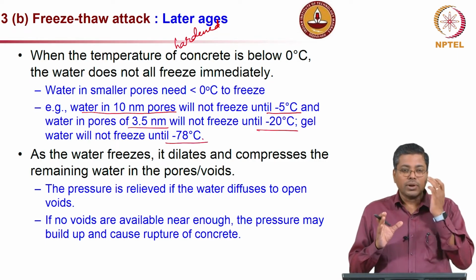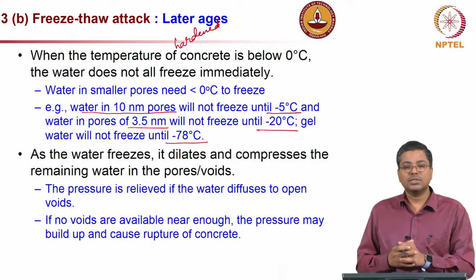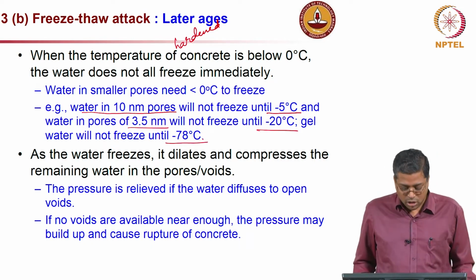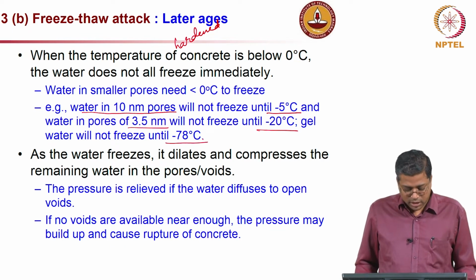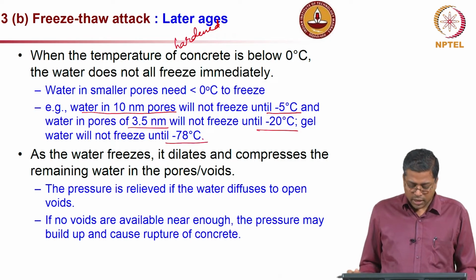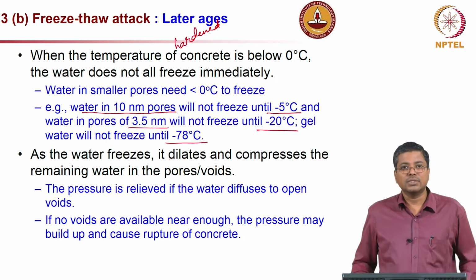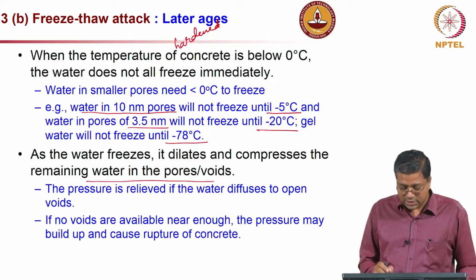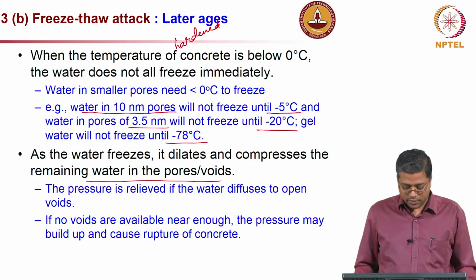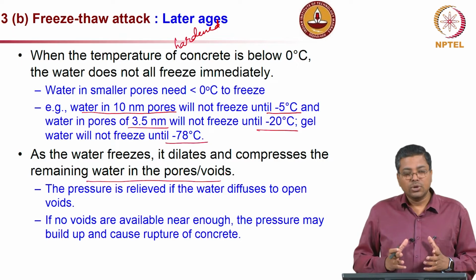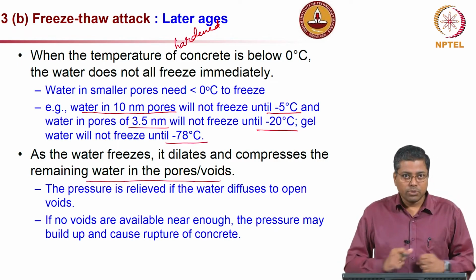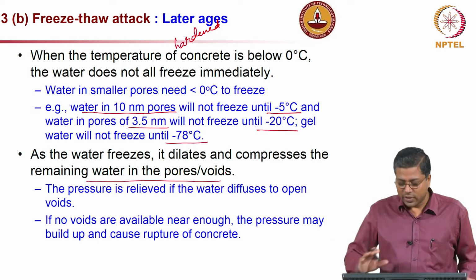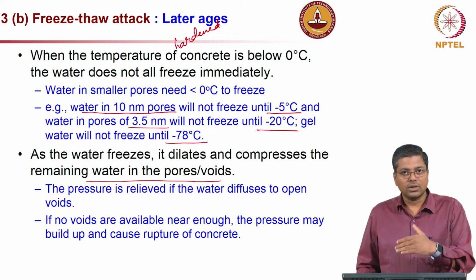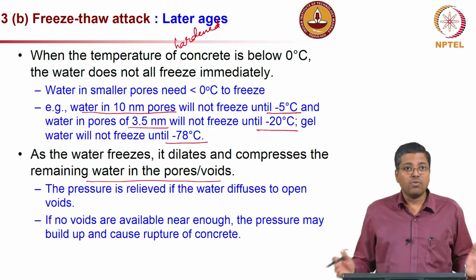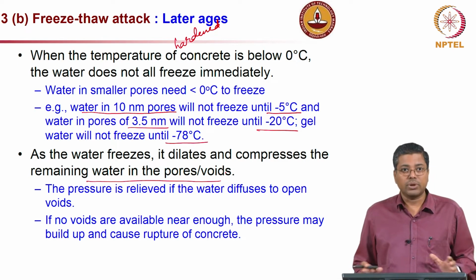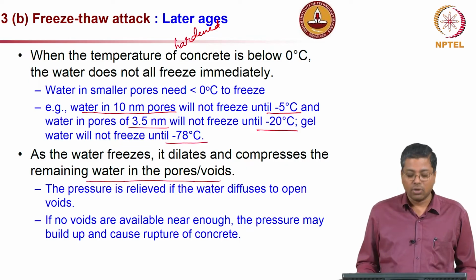So, at the same temperature, what it means is there could be some water which is already frozen and some which is not frozen, depending on the size of the pore where the water is staying or occupying. And as the water freezes, it dilates and expands and compresses the remaining water in the same pore. During this process of dilation, it pushes the water, and that pressure is relieved if there is a sufficient pathway available for that water to move into another pore or void, and if no voids are available in the near vicinity, then the pressure may build up, which eventually leads to cracking or rupturing of concrete.